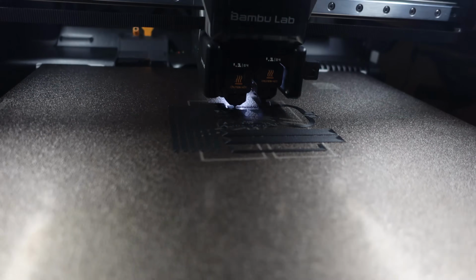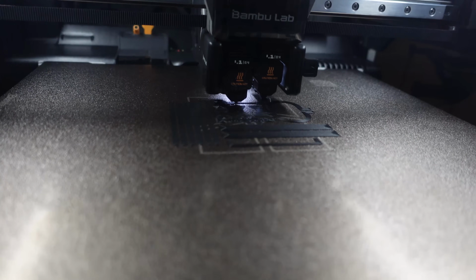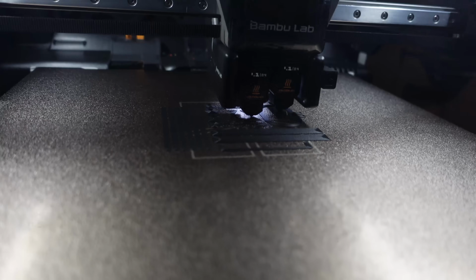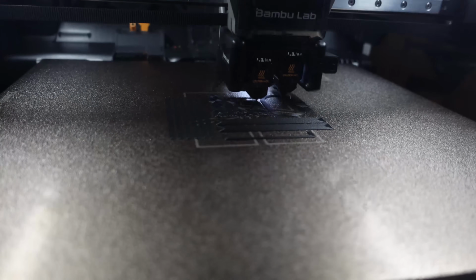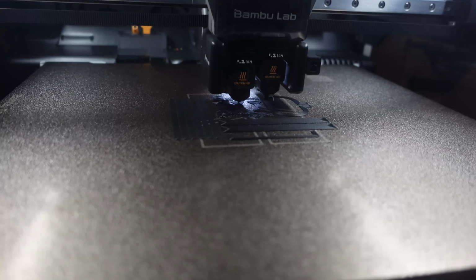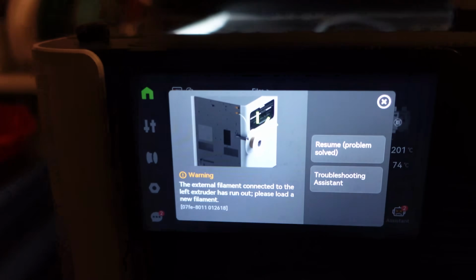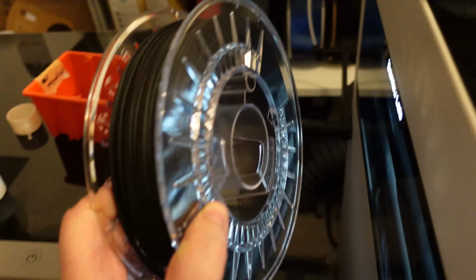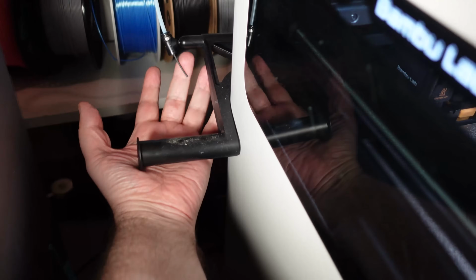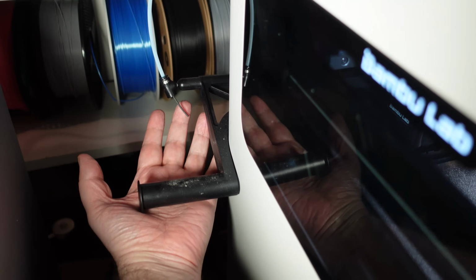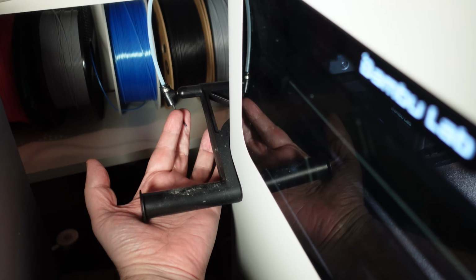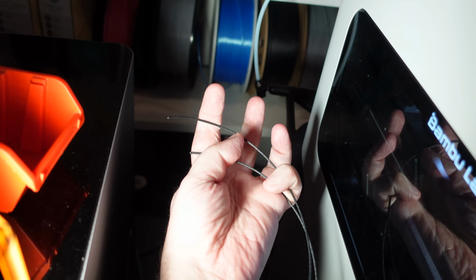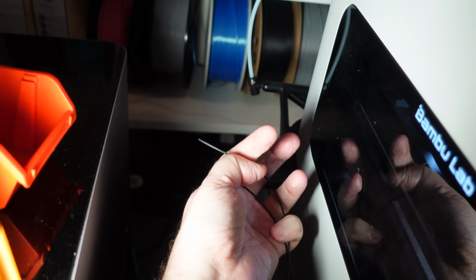Start of the printing is good, and I know it will be fine, only I'm hoping it is not too fast, and you will see a decent layer adhesion. Wow, broken filament. Yes, the brittle one. I was just pushing in the filament and it already broke. New record, this is one of the most brittle filaments I ever tested. Just a little bending and it's already broken.